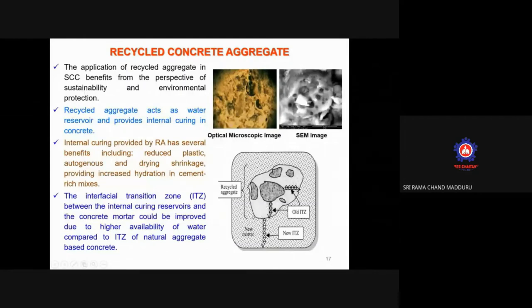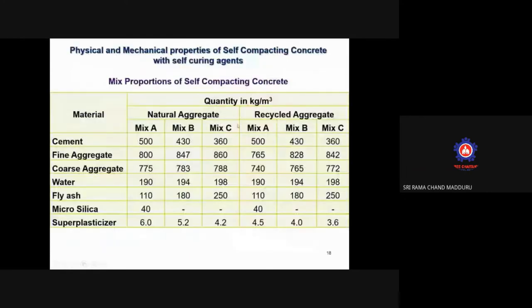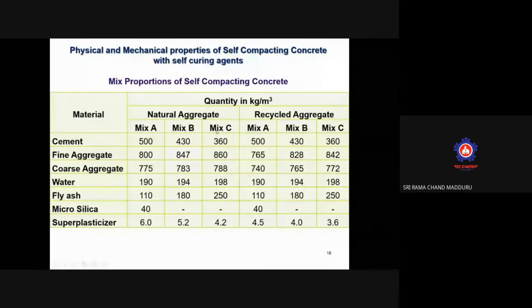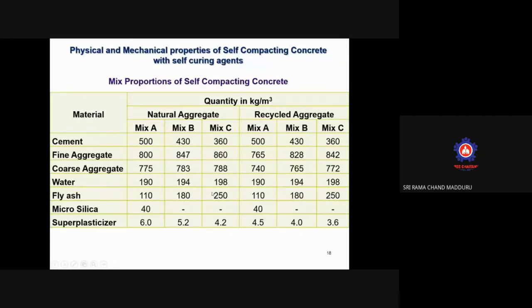And whereas when you are adding, a new interface zone will be there. So the presence of pores in the concrete, this recycled concrete aggregate can be as similar as lightweight aggregate. So the pores present in the recycled aggregate can be used as internal curing agents to improve the performance of concrete. So I am showing you three mixes that we have taken to achieve 70 MPa strength, 50 MPa and 30 MPa strength.